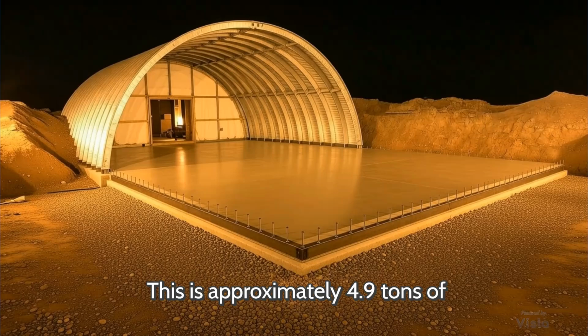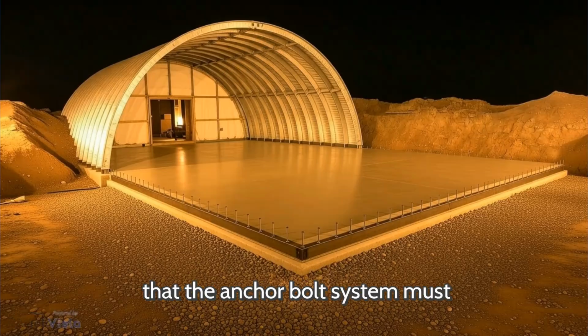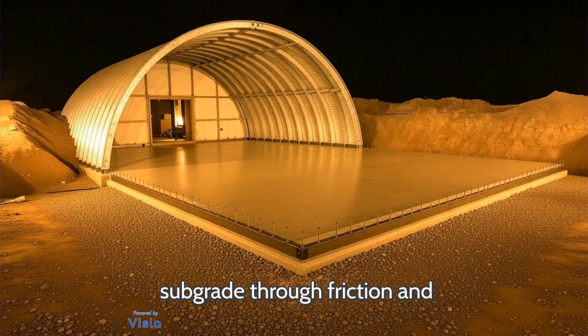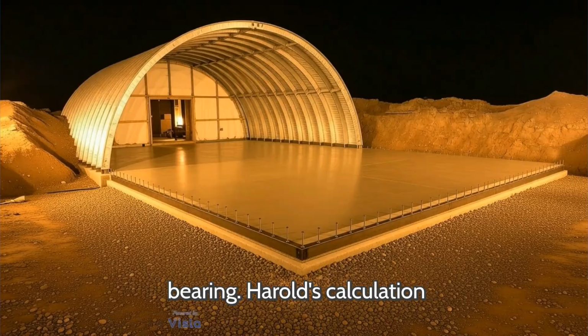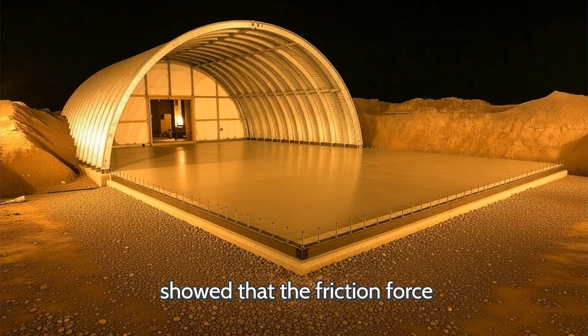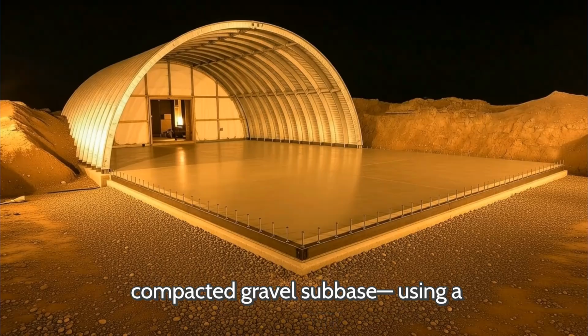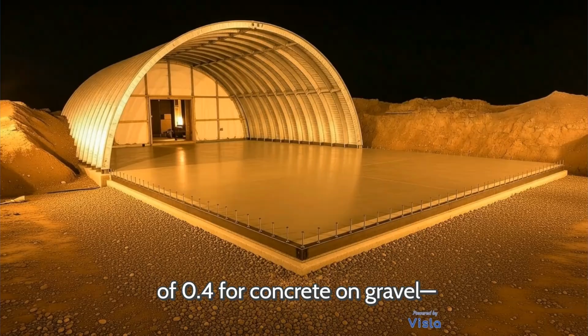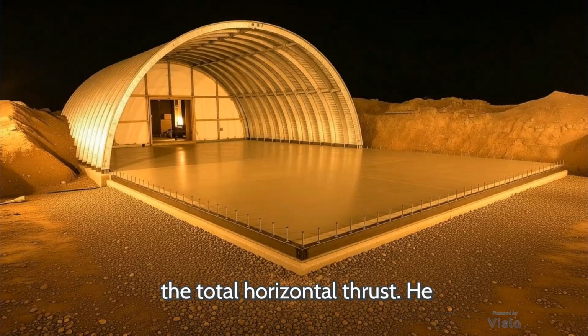This is approximately 4.9 tons of horizontal outward thrust per linear foot of arch base, a force that the anchor bolt system must transfer into the slab, and that the slab must transfer into the subgrade through friction and bearing. Harold's calculations show that the friction force available between the 1,152 square foot slab and the compacted gravel subbase, using a conservative friction coefficient of 0.4 for concrete on gravel, was more than adequate to resist the total horizontal thrust.